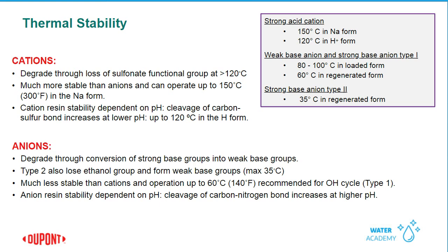So, cations can degrade through the loss of their functional groups, but anions degrade in a slightly different way. If you have a strong base resin, it can convert some of the strong base groups into weak base groups, which will still work as far as removing mineral acidity. However, it might have a loss in the silica capacity. They could also degrade through the total loss of the functional group as well.